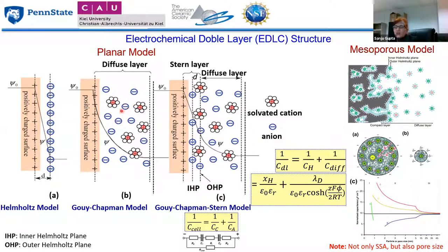And as you can see here, these ions are solvated, meaning they are surrounded by water molecules. So these are called solvated ions, cation or anion. The corresponding double layer capacitance is given by 1 over C_H plus 1 over C_diffusion, since they are in series. As you can see here, it is primarily dominated by the Helmholtz capacitance. So C_DL is basically equivalent to C_H, because C_diffusion is kind of large, so this term cancels out. And this all comes from electrostatics, the Poisson equation. Back then, it was believed that this is only a parallel plate capacitor, as I'm trying to describe. Although in most circumstances this model works fairly well, later on we learned that it's not